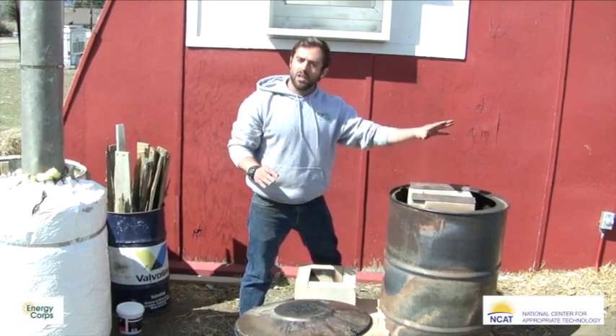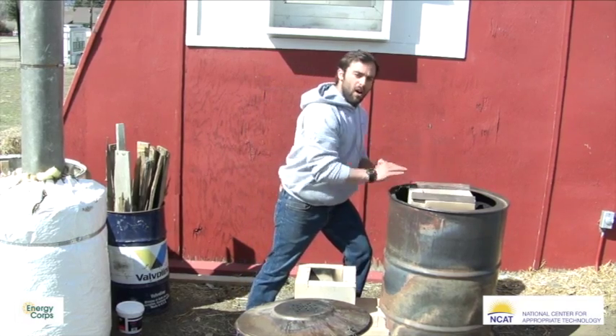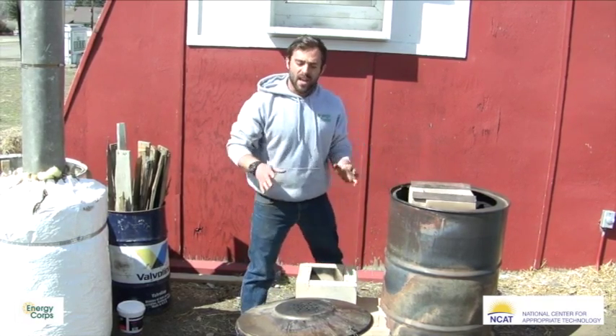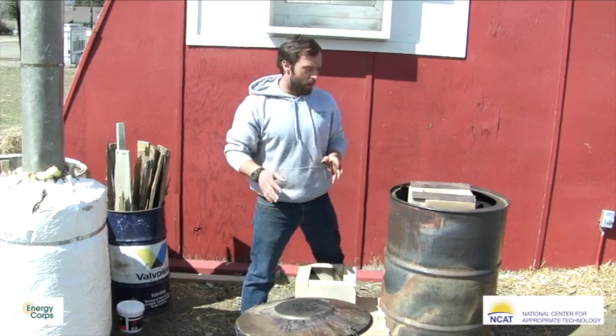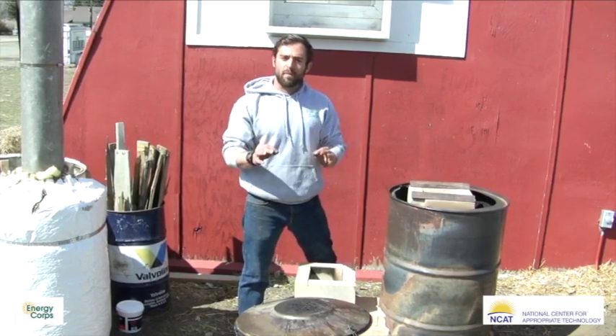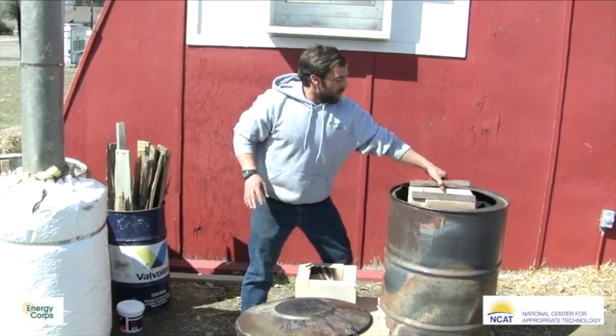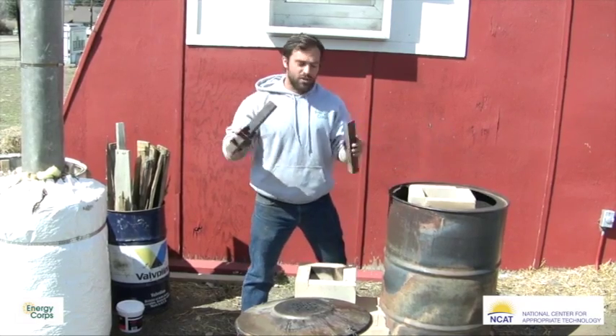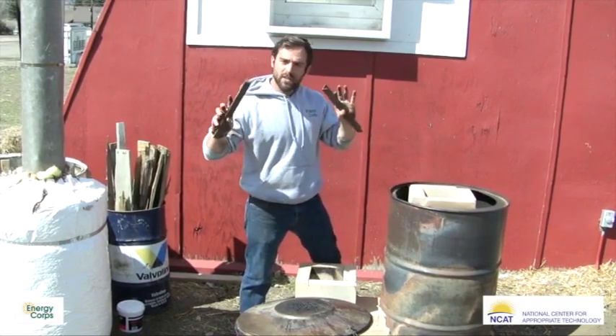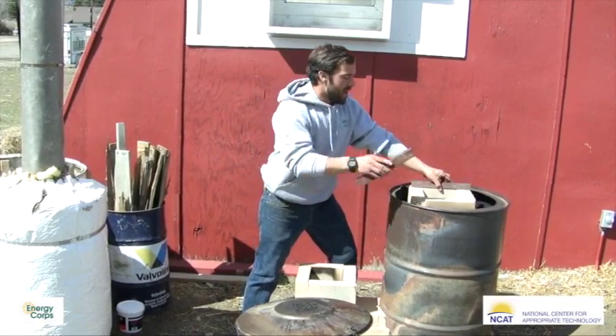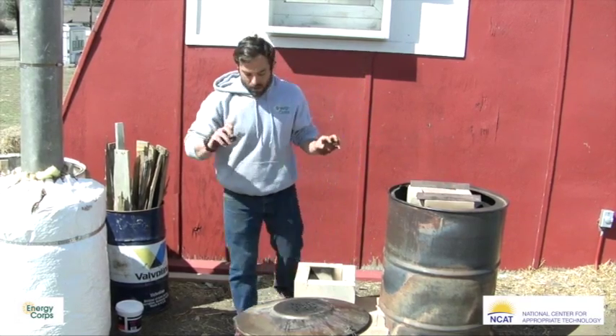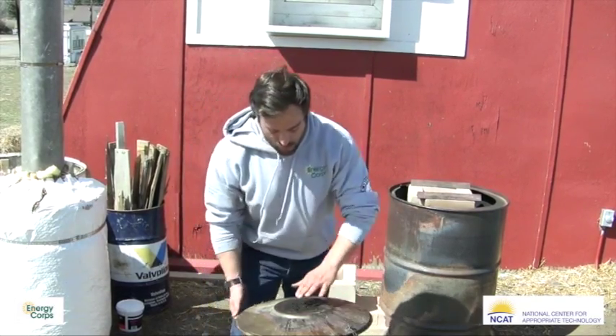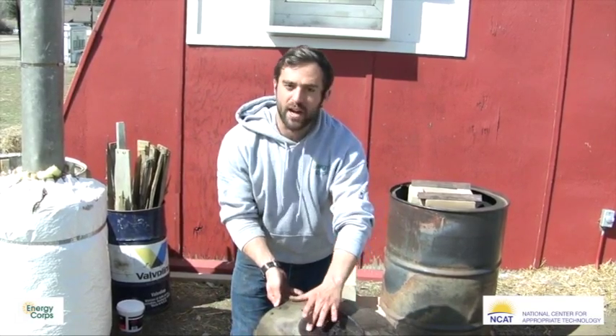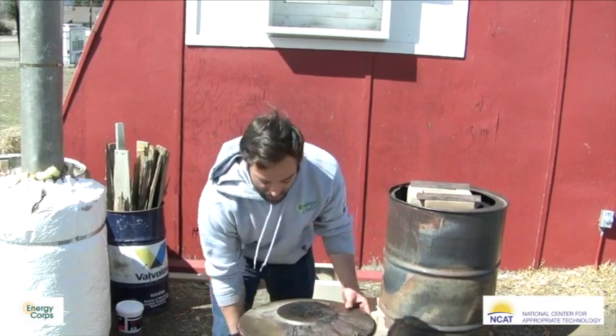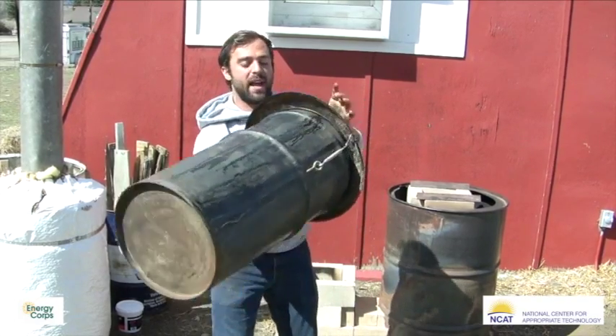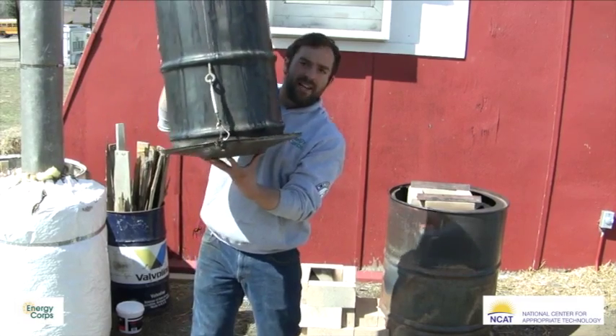When operating, the hottest portion of this kiln is going to be right here on top of the heat riser itself. And this is where we want to place the oxygen limiter retort. We don't want to place it right on top of the heat riser to block oxygen. We want to elevate it on what I have here is 2 pieces of angle iron. So these pieces of angle iron sit right on top of the heat riser, and the retort sits right on top of that. Also, when putting the retort on, you want the place you've created for your wood gases to escape to be at that hot portion to hopefully flare off. So in our case, we're going to load this retort upside down on top of the kiln.